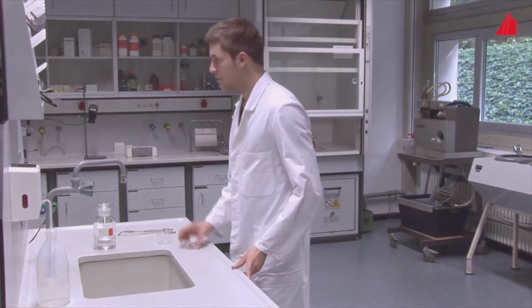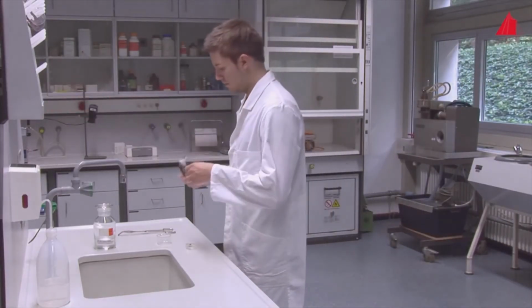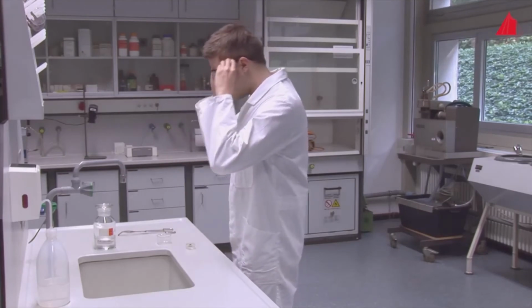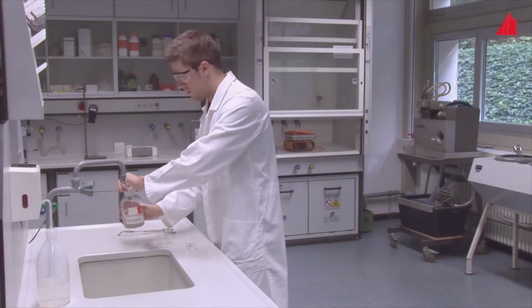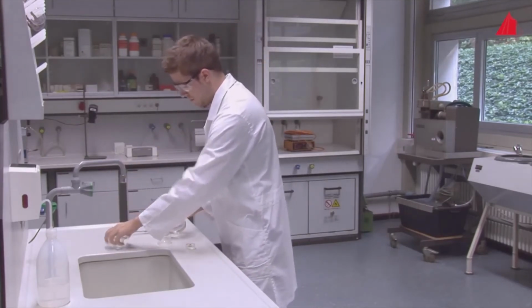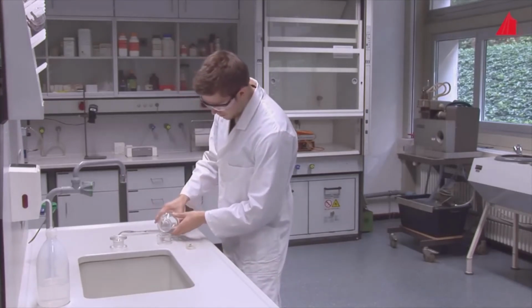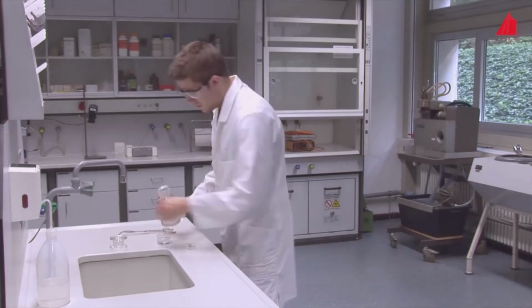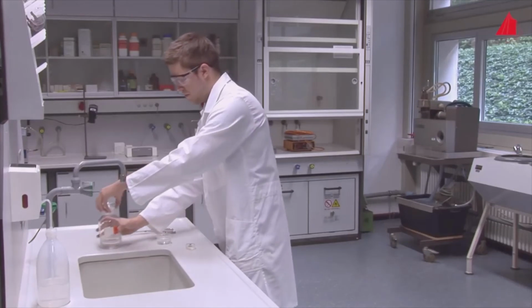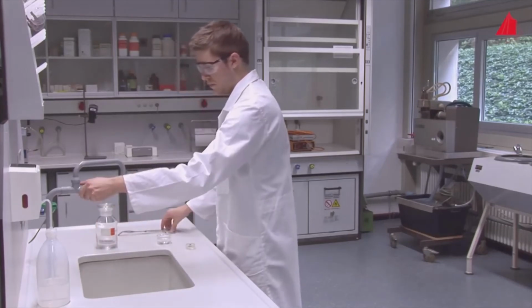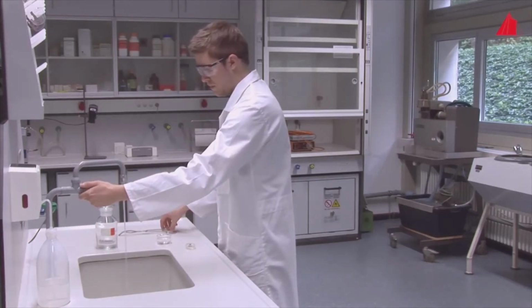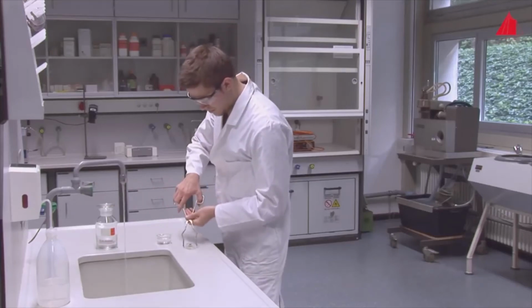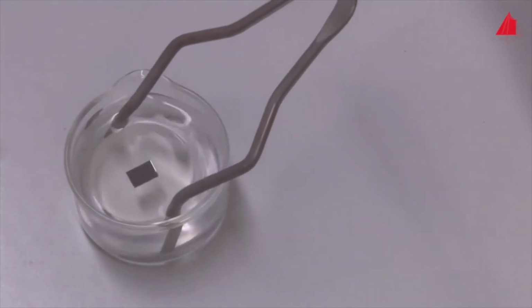To do this, our material tester protects himself with a lab coat, puts on safety glasses and pours the etchant into a small glass bowl. The etchant consists of a solution of 10% of concentrated nitric acid in alcohol. Now he turns on the water tap, picks up the freshly polished microsection with gripping tongs and immerses it for a few seconds into the etchant.